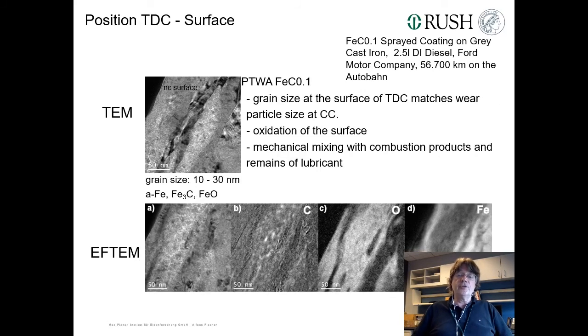At the top dead center, it became even more chaotic because you find a laminated structure of former coating material, of remains of the piston rings, of remains of combustion products, everything mixed into everything. And again, everything was nanocrystalline. So we thought that, as in the combustion chamber, as well as the top dead center, this nanocrystalline stuff that comes in parts from the coating and in parts from the counterbody, as well as from the environment on combustion products, has a protecting surface because the wear rates were really small.